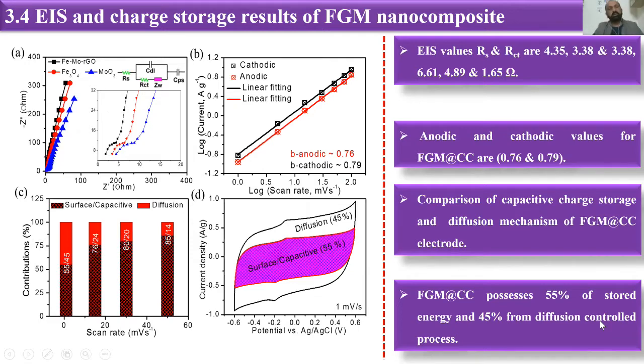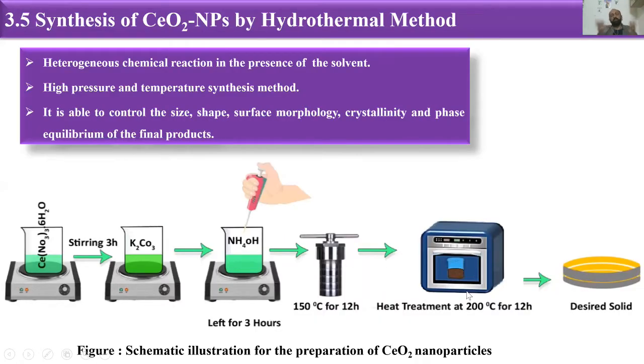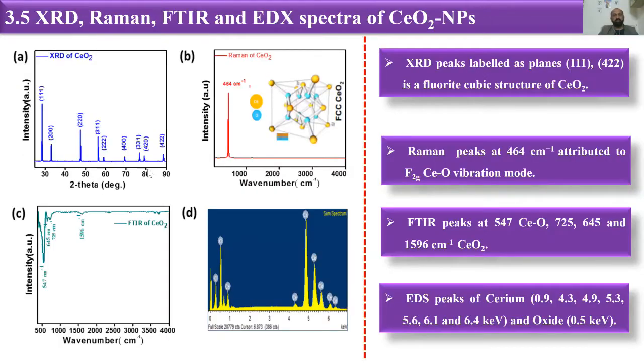Then last, we have done the synthesis of our cerium oxide nanoparticles by hydrothermal method, using the precursors and treating at different temperatures, and we have got the desired CeO2 nanoparticles. Then we have characterized these particles with their analytical property characterizations, with XRD, Raman, FTIR and EDX spectra, and all the peaks which we have got are present in the CeO2 nanoparticles.